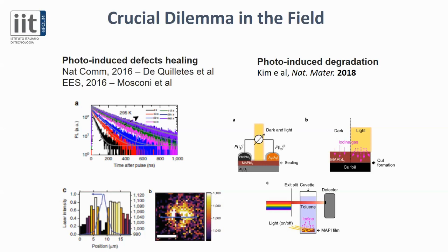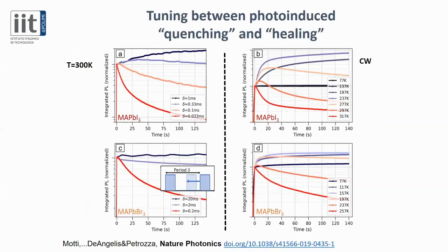Under illumination, the emission performance, for example, was improving. Some of us were observing photo-induced degradation. And you can understand that this is an important point if you want to use this material as a photovoltaic system, when you need to irradiate it for many hours. What we found, kind of solving this dilemma, is that the two phenomena are actually coexisting.